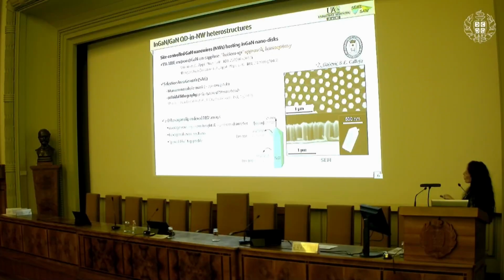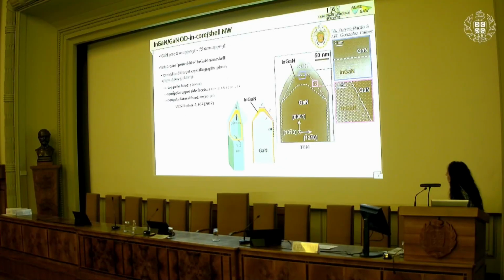You also see that the top of these nanowires has a pencil-like profile that is defined by the semi-polar S planes. And actually, the morphology of these nanowires is core-shell, which means that there is a thin indium gallium nitride shell that is embedded inside the gallium nitride nanowire, as you can see in this illustration. As confirmed in transmission electron microscopy characterization of individual nanowires, this thin indium gallium nitride nanoshell is formed on different crystallographic planes with different orientation. So as you can see, we have here the top polar facet, then the semi-polar side facet, and the lateral non-polar.